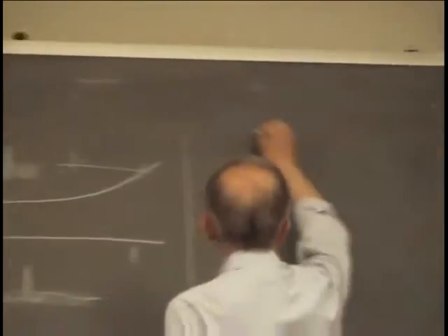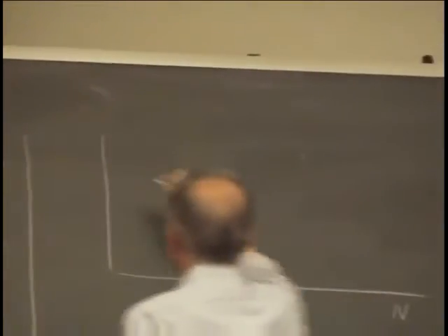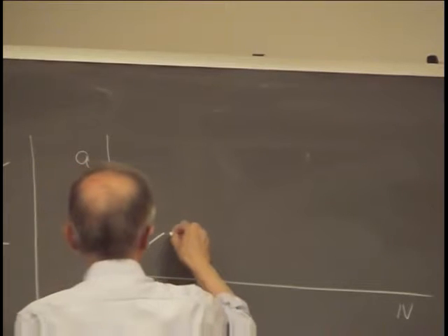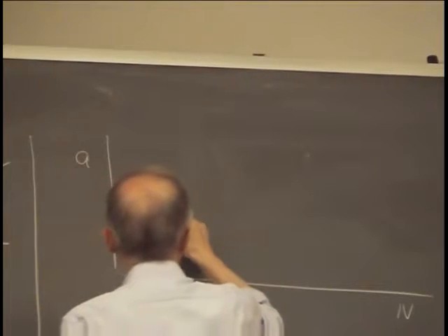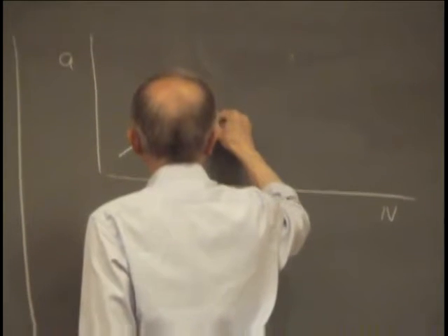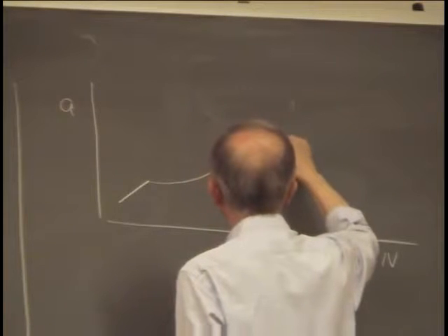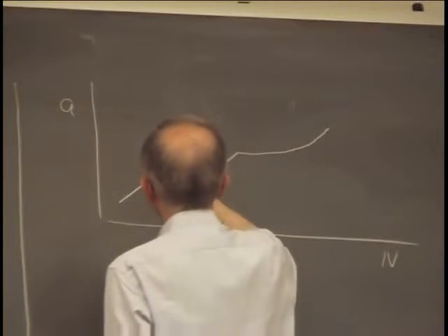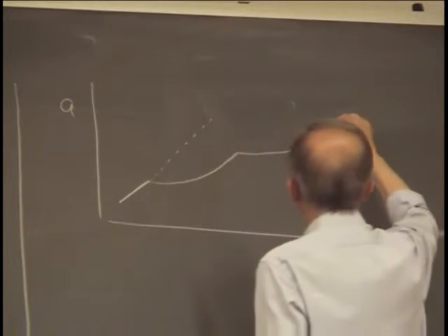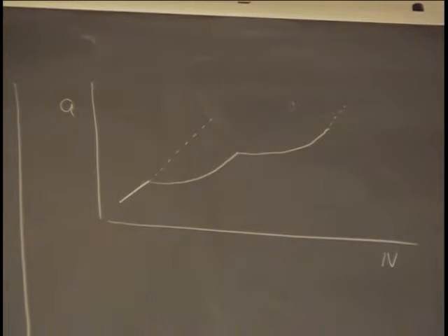And the effect is then the following. We have crack propagation with this rate here. A single peak overload is applied. The crack here is retarded. And then another single peak overload is applied, and the crack is again retarded. And you see the effect can be very substantial. And of course, it can't be overdone, because at the end, the K max, the maximum K value that we apply, can be bigger than the critical value of the fracture toughness of the material. So this has to be avoided, of course.